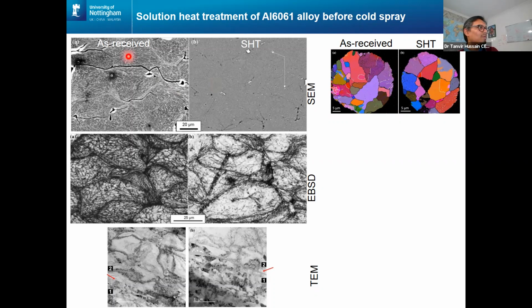That's not true anymore. As received, there's quite a lot of particle to particle interface issues there, as you can see with the cracks. So that's one particle, another particle, but they're not bonding very well. Compared to that, solution heat treated ones are forming much better. Band contrast images, you get a better pattern quality when it's a solution heat treated one, and it suggests a lower amount of lattice defects, which also exhibits a darker contrast due to a high number of grain